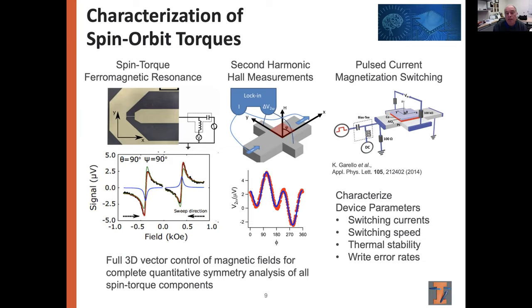But beyond that, we can also then take the Weyl semi-metals, integrate them with a simple ferromagnetic layer, and using a fairly straightforward pulsed current magnetization switching setup, we can do statistical measurements that allow us to characterize device parameters that are really important for, let's say, memory applications. So we can characterize, in particular, switching speeds, switching currents, thermal stabilities, things like write error rates. And this allows us to do fast statistical analysis of these properties.